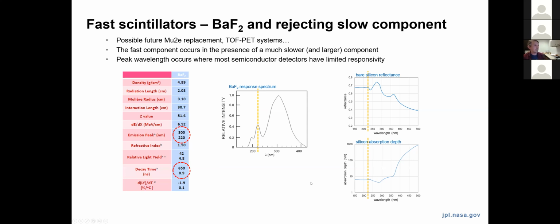We wanted to see if we could do better by integrating these devices directly on a detector. Some of our initial interest in this work was for a high energy physics application in collaboration with Professor Hitlin at Caltech, who was interested in creating a readout detector for a barium fluoride crystal scintillator. The crux of the problem is that barium fluoride is an interesting material for this application because it has a very fast scintillation component that is centered near 220 nanometers, but unfortunately it comes in the presence of a very slow scintillation component at longer wavelengths. And so that influences timing experiments using these types of detectors.